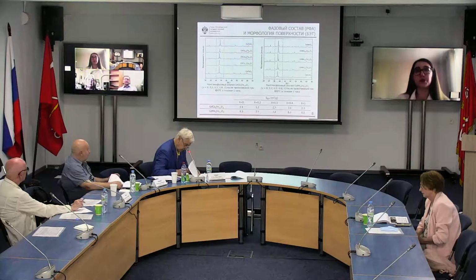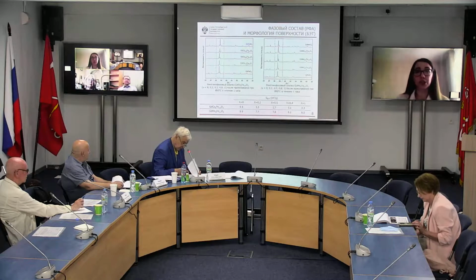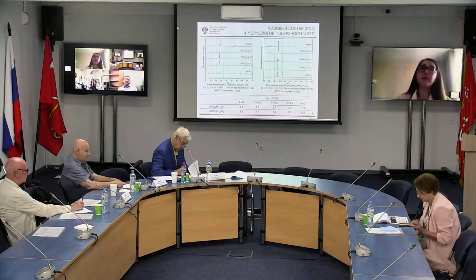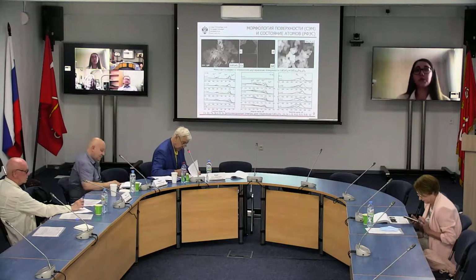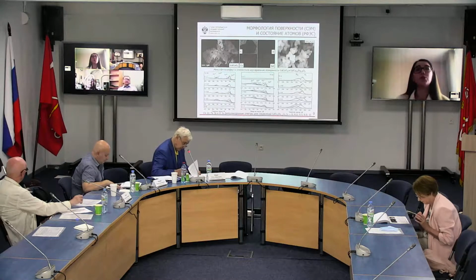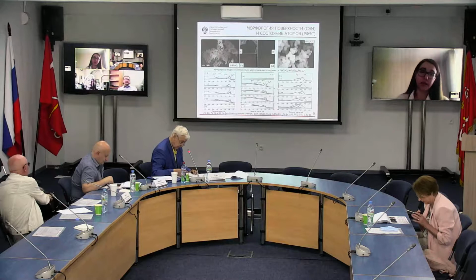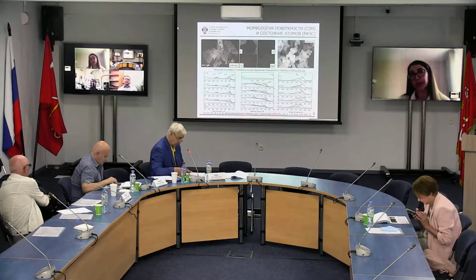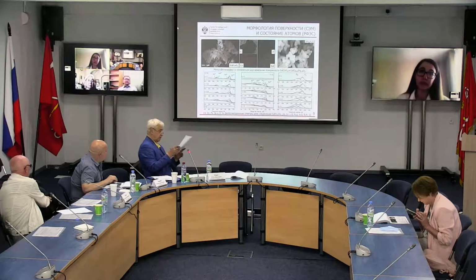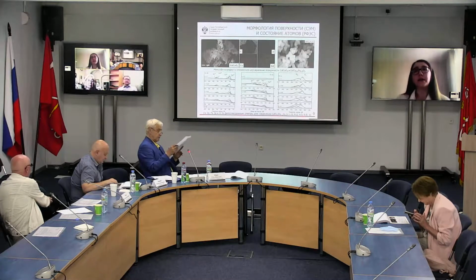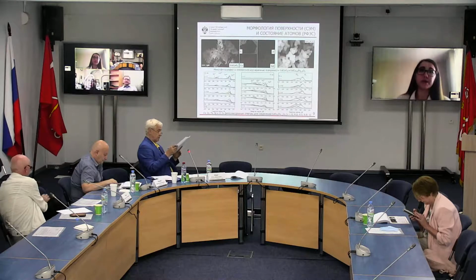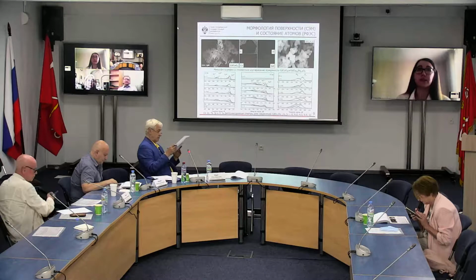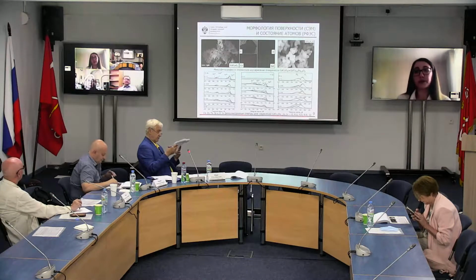At the same time, the values of surface area were higher for these oxides than for similar compounds obtained by the ceramic method. We also use SEM to study morphology, and all the complex oxides demonstrate a similar homogeneous, volumetrically rough surface formed by particles of different size and form. To study the content of the surface, we used X-ray spectral analysis and carried out elemental mapping of the surface. The results show that gadolinium, iron, cobalt, and manganese are evenly distributed, and their content is close to theoretical values.